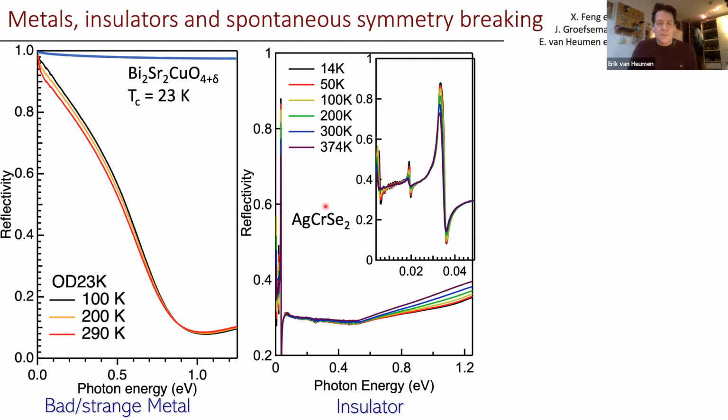That's the key difference that comes out of essentially the Drude model. These line shapes that you see here are optical phonons, and here they're really quite large. I promised to show you a little bit more later about optical phonons in cuprate data. They are actually there, and you can't see them because the free electrons are screening these excitations. That's another one of the differences.